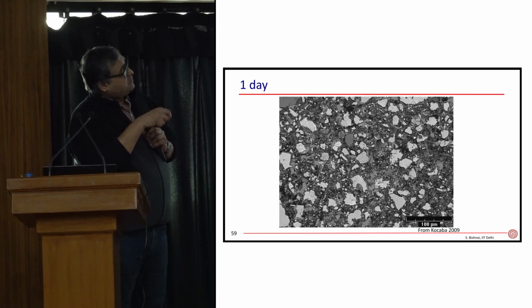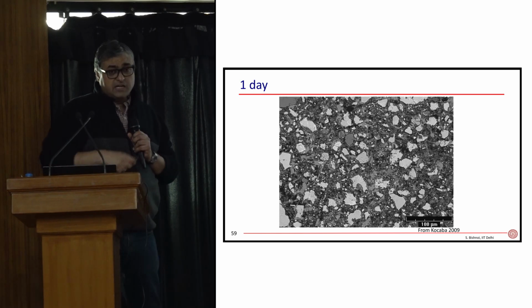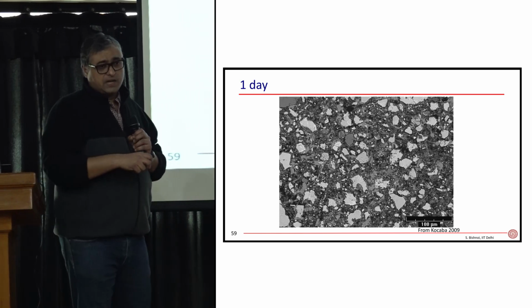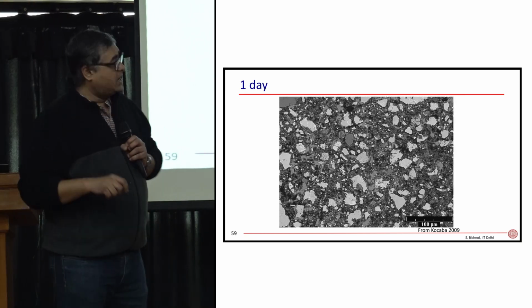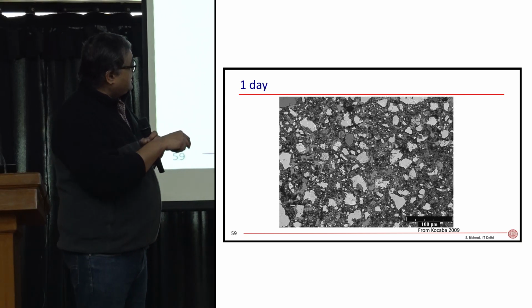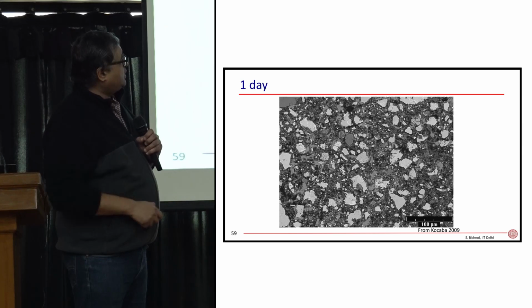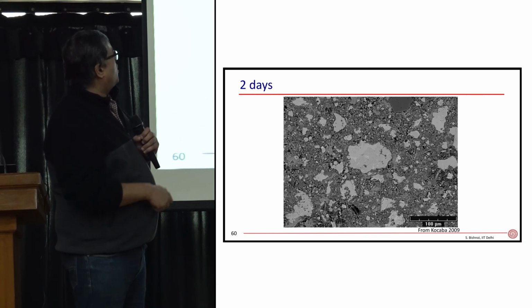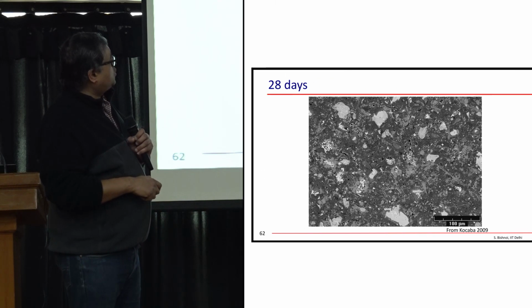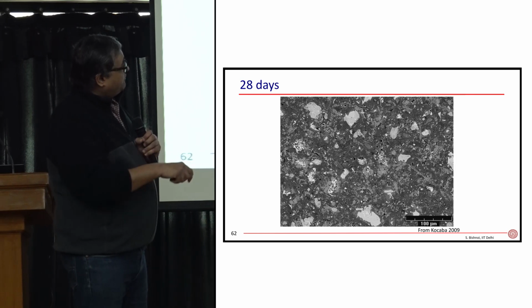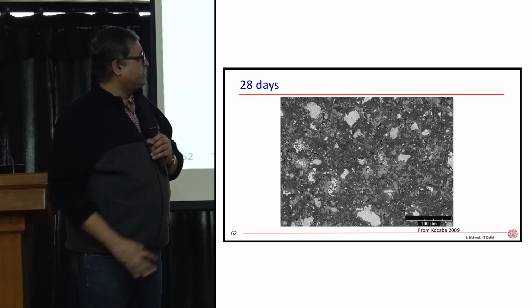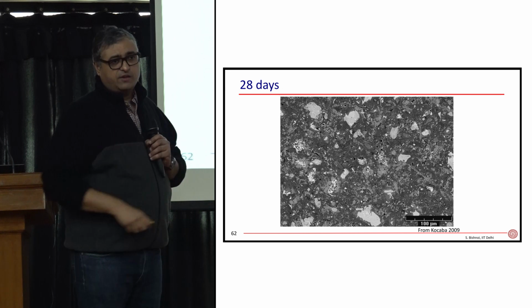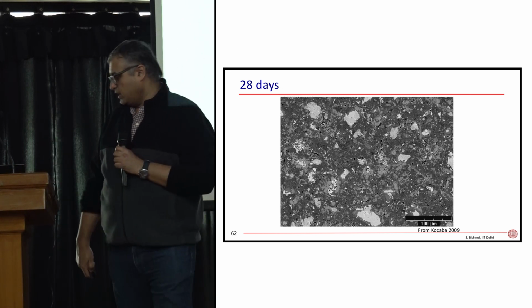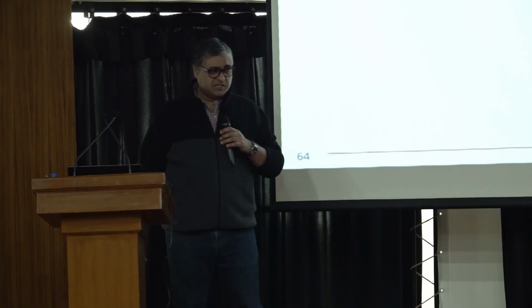In these micrographs, at one day you have more product. The brighter materials in these microscopic images are the solids, and the black part is the pore. You see there is less pore compared to the one at 12 hours. Even fewer pores going down to 28 days. You end up with a paste, a matrix that contains a lot of solids, very few pores, everything properly bound together. And ladies and gentlemen, that's how hydration happens. Thank you.